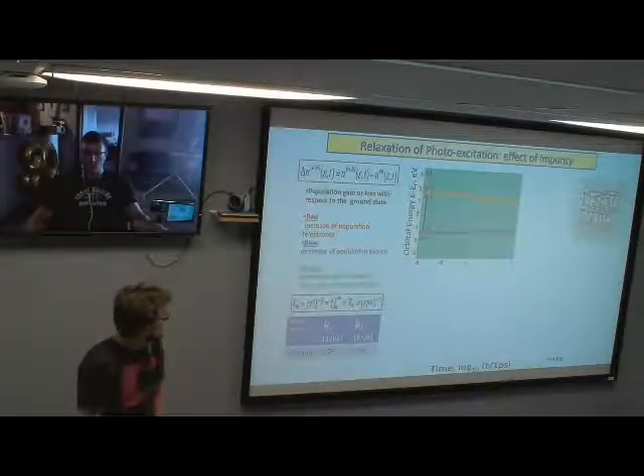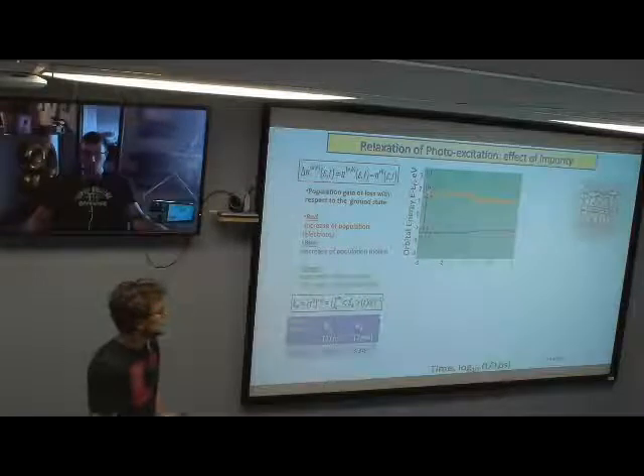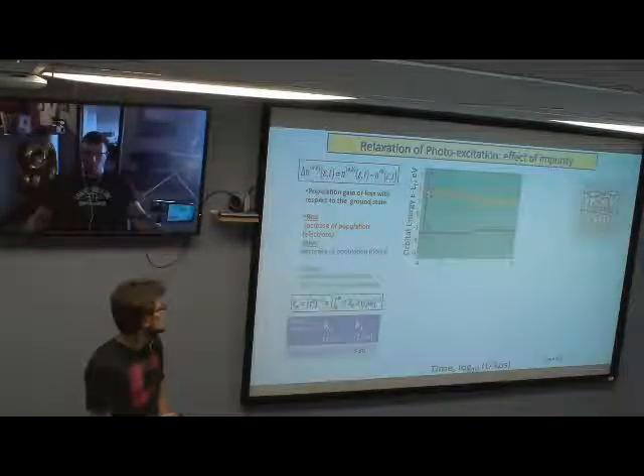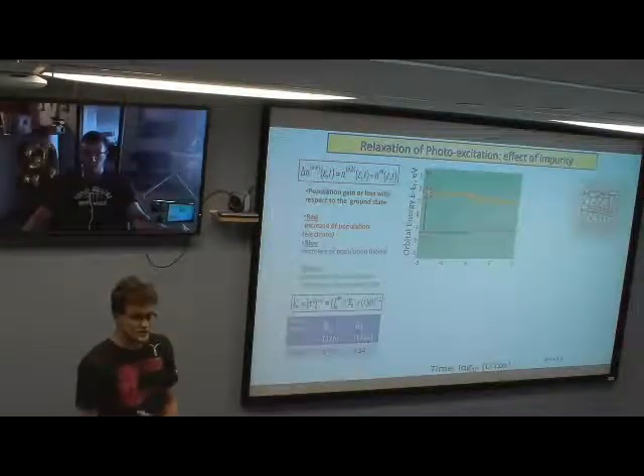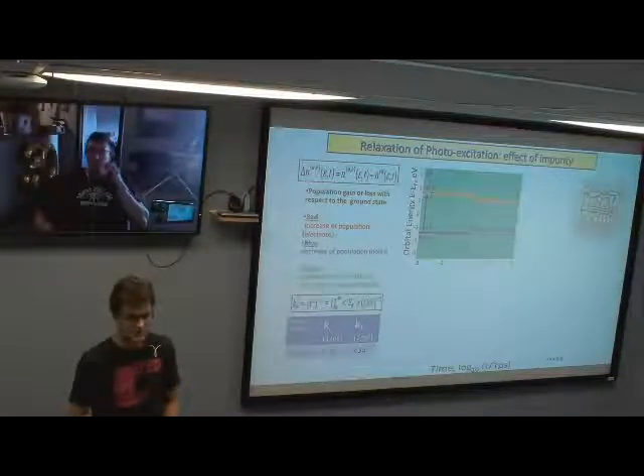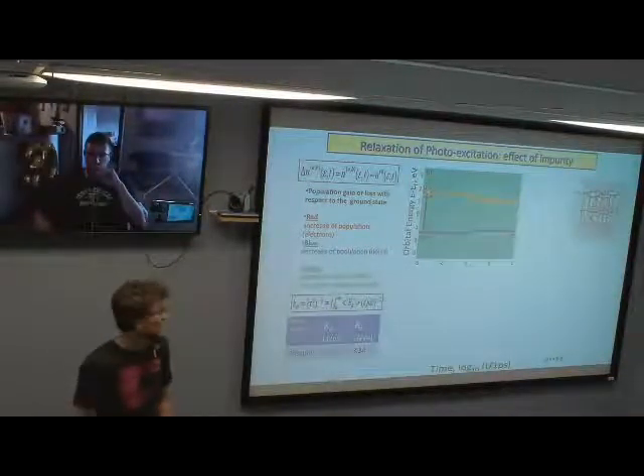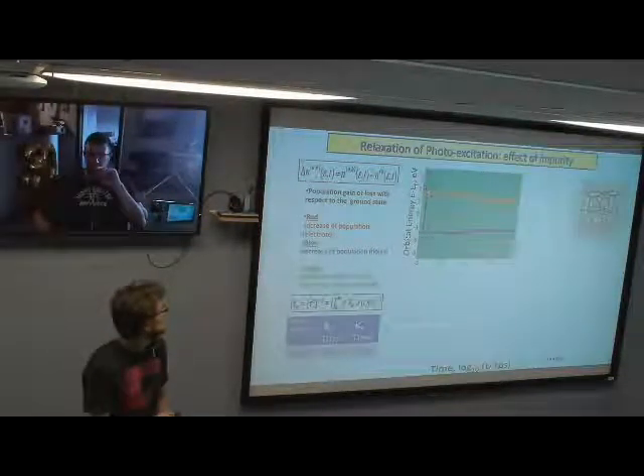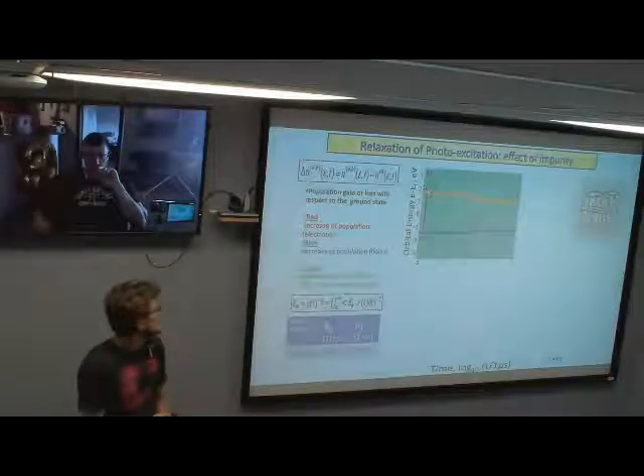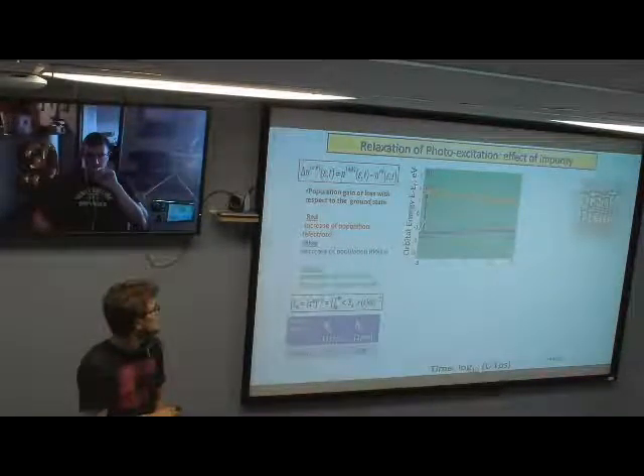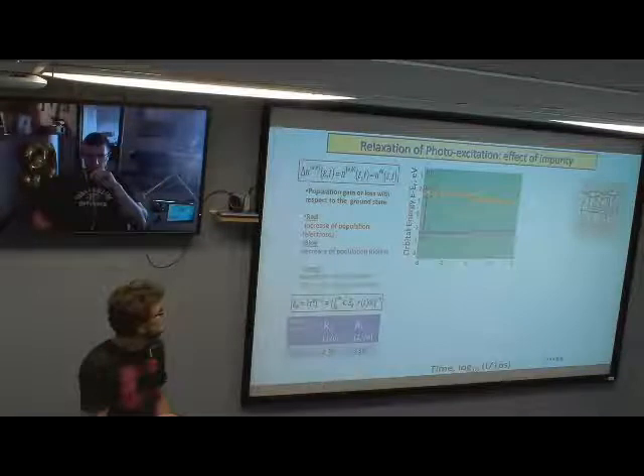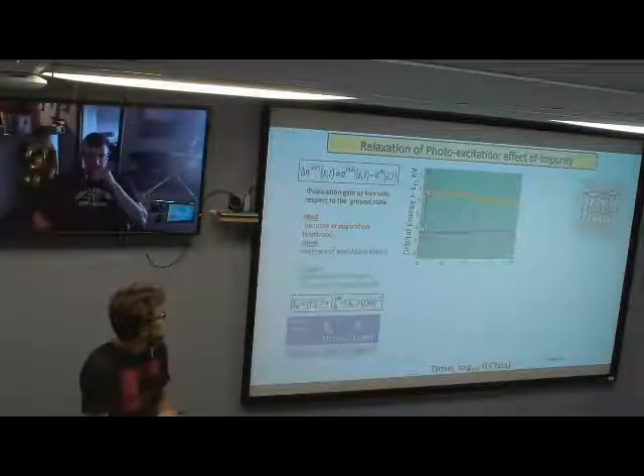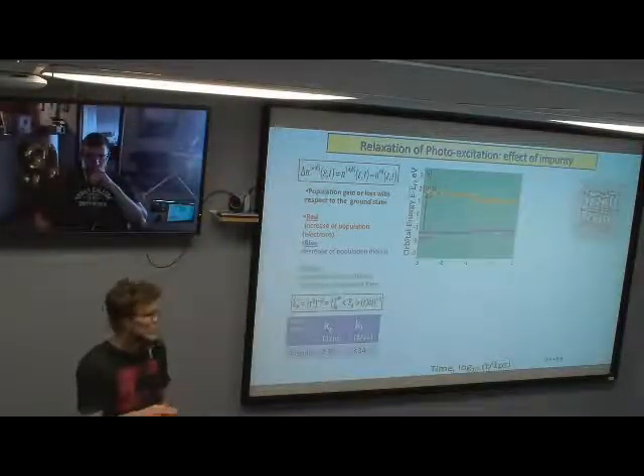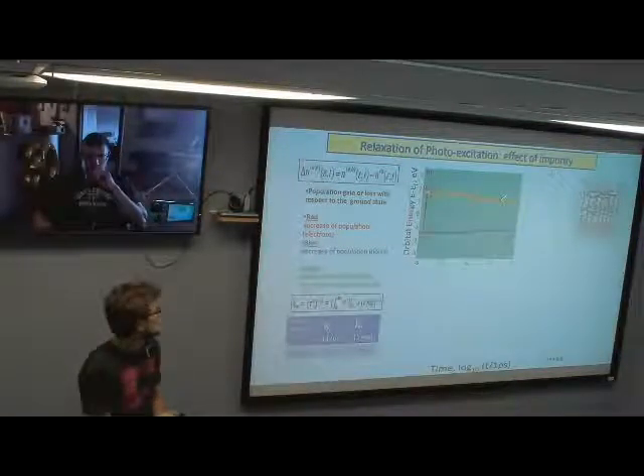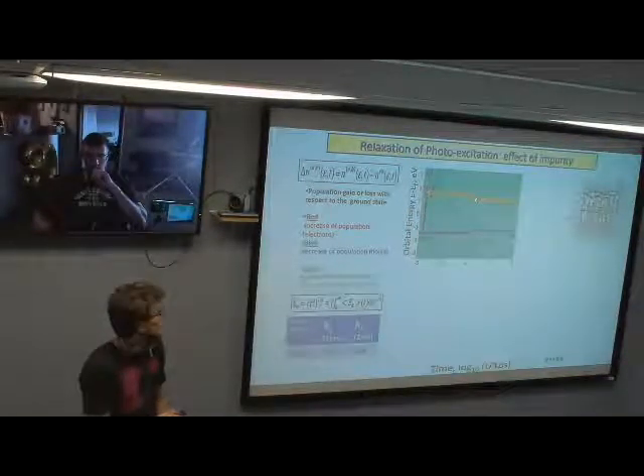And so to use these Redfield tensors, we start off with an initial condition, which we choose based on oscillator strengths or most probable excitations in the system, or ones we think are interesting anyway for initial conditions. So here we start out with LUMO plus 9, or HOMO minus 9 to LUMO plus 10, where in these figures, the green represents a reference energy density. So basically no change in energy and time.